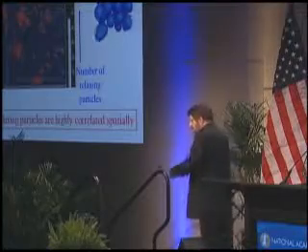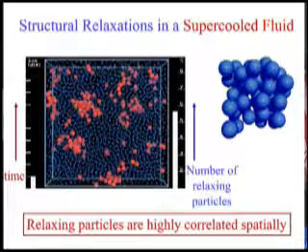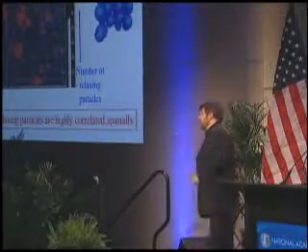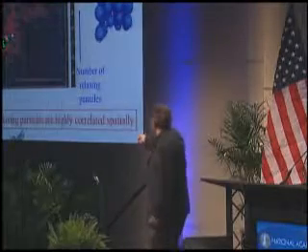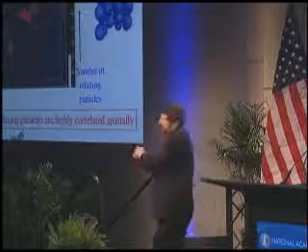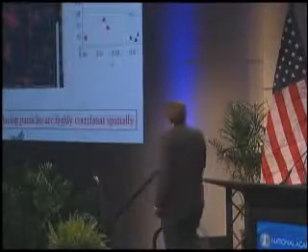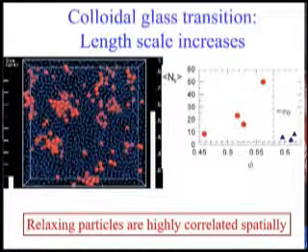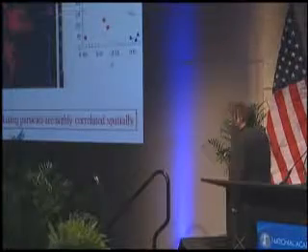More commonly we concentrate the particles. This is not a computer simulation, but rather real data looking at the motion of concentrated particles. This is a way that we can study something like a glass — a supercooled fluid that wants to become a solid, that wants to become a glass. The fact that it's a fluid means that the particles have to move large amounts, not individually but collectively. There are large clusters of particles that move, literally leaving room for other particles behind them. You can measure the length scale of this, and the length scale of these motions gets larger and larger as the sample approaches the colloidal glass transition — telling us about how it gets stiffer and slower because of larger and larger length scales of relaxation motions.